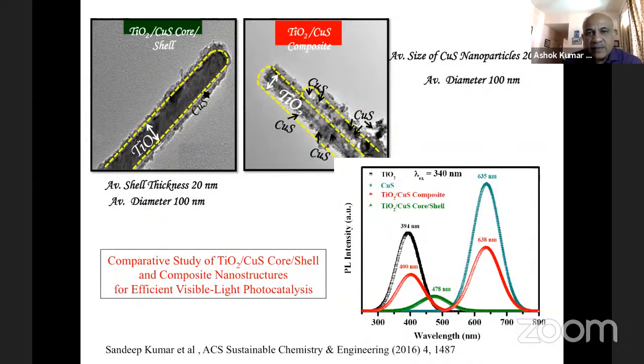This is another design. Here, what we compare is a semiconductor particle, a nanorod of TiO2, and you put another semiconductor which is in the visible, like copper sulfide. If that is uniformly on top of the core material, it has some efficiency. But if it is like particles on top of the rod, but not uniform, it will have a different efficiency. So we compared the core shell type of rod with a composite kind of material. The materials are the same, copper sulfide and TiO2. Only the morphology is different.